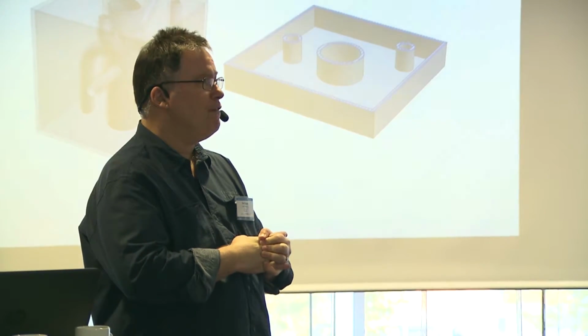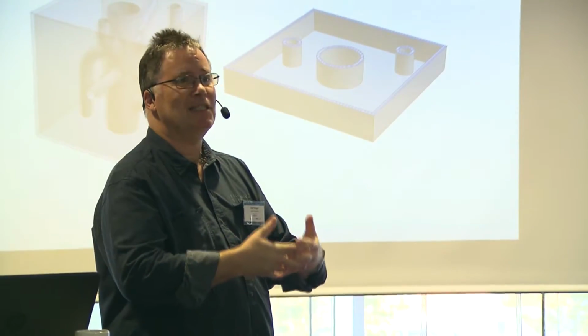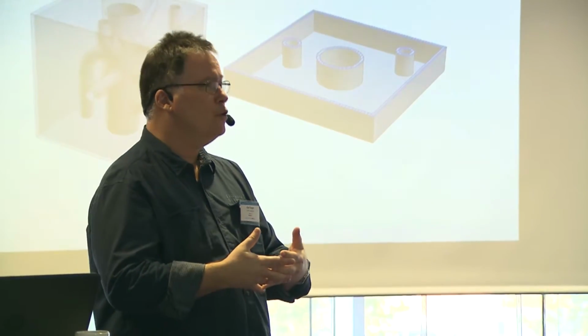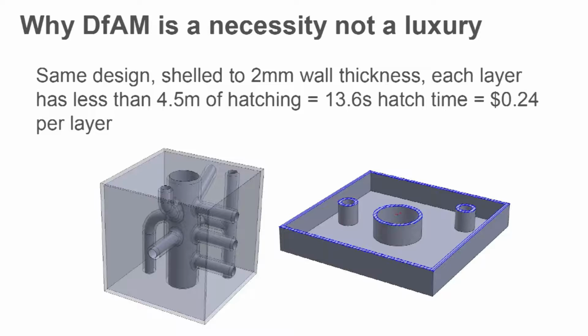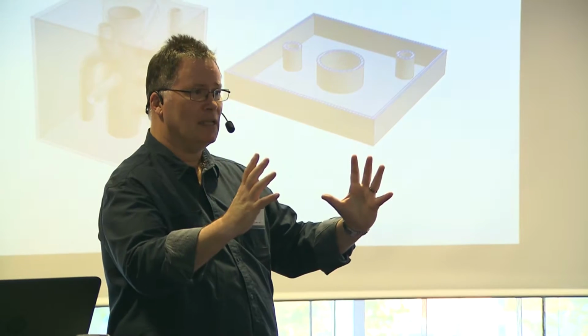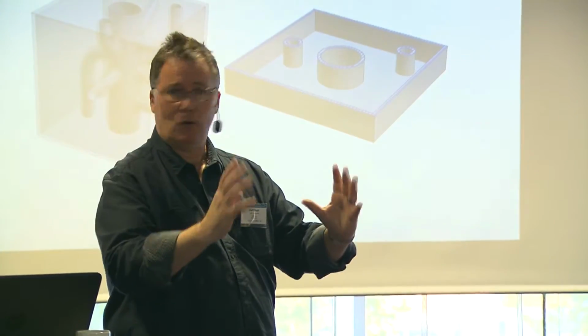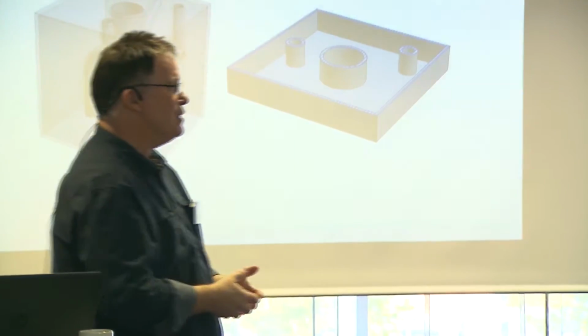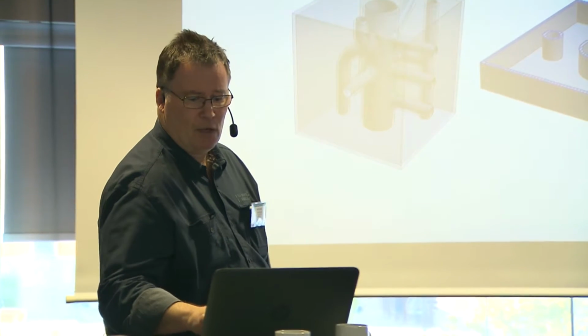So that's almost a 95% saving in terms of the distance the laser has to travel, therefore a huge reduction on print time. And here we're down to 13 seconds. So we're down from over 5 minutes per slice to 13 seconds per slice. Huge saving already, and it'll look identical. Of course, the inside will be filled with powder or with support material that you may decide you can leave in or not, depending on how you want to do it.